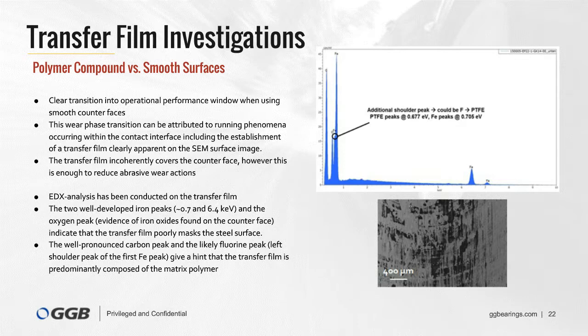These are the information of the steel counterface. What we also see is that we have a well-pronounced carbon peak, and we also have a likely fluorine peak, which is the left shoulder peak of the iron, giving a hint that the transfer film is predominantly composed of the matrix polymer with a contribution of PTFE.